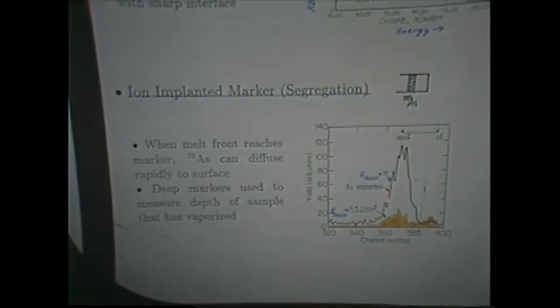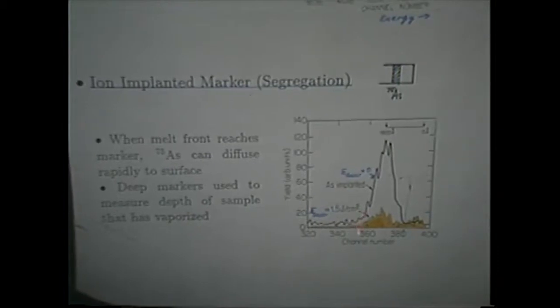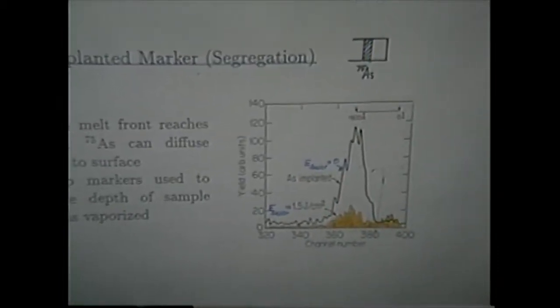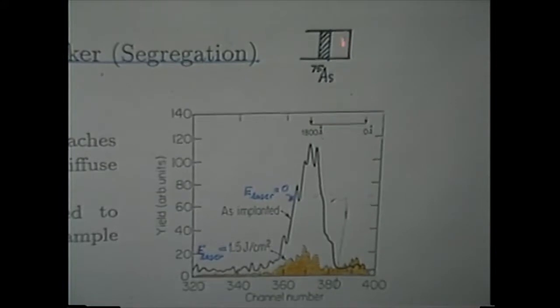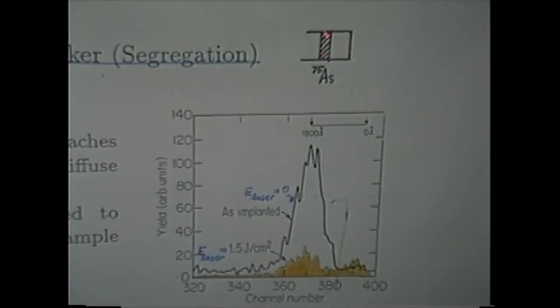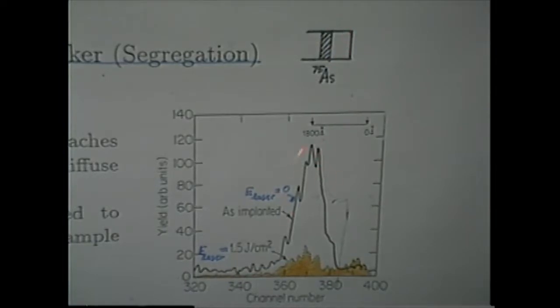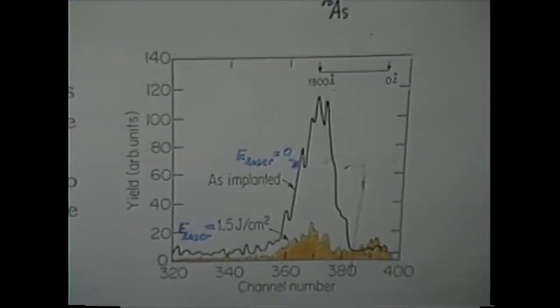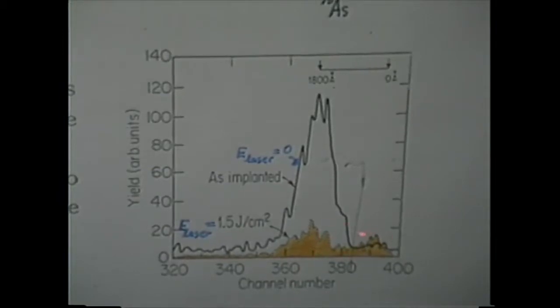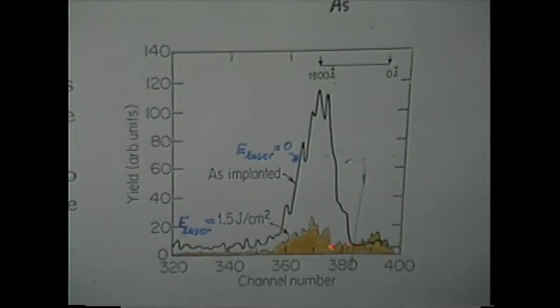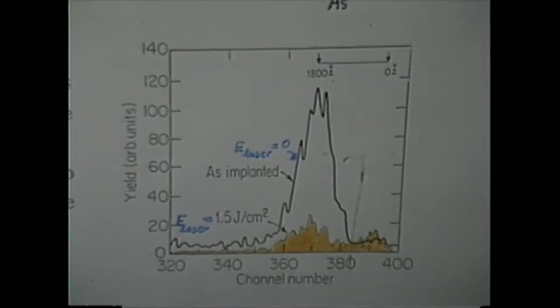When the laser energy is 0 or very small, we get this profile from the Rutherford backscattering. As the laser energy increases, you could think of the melt front moving in from the surface inside the silicon region, still far from the arsenic implant. So when we're over here, we still retain essentially the same arsenic line. But as the melt front approaches, the arsenic joins in the puddle and segregates to the surface, and we see that effect here. Much of the arsenic leaves as it melts, and the rest begins to segregate to the surface. So that experiment is highly suggestive of having molten silicon. The Raman experiment similarly can be explained in terms of melting silicon.